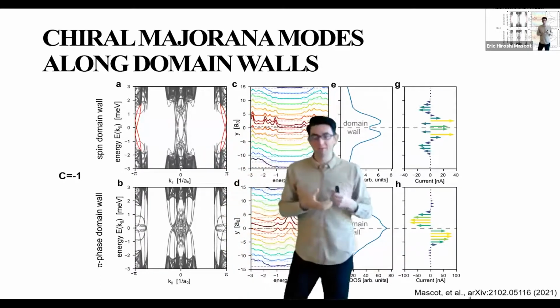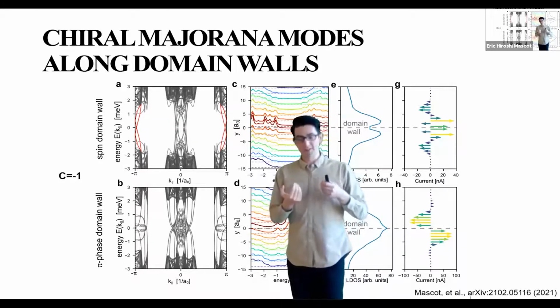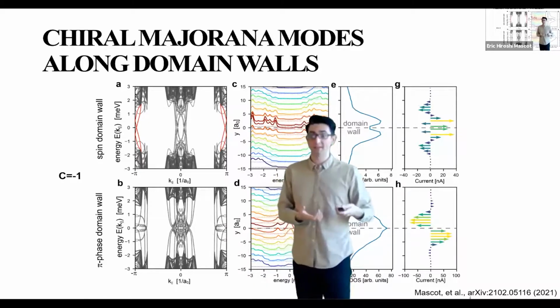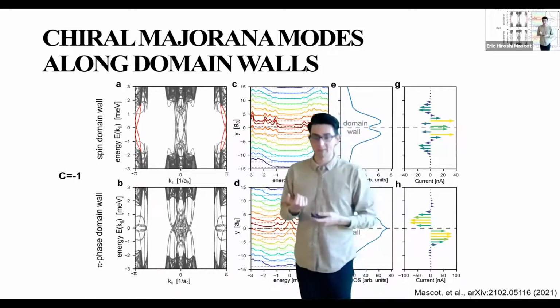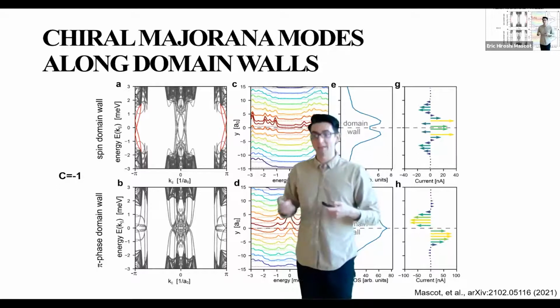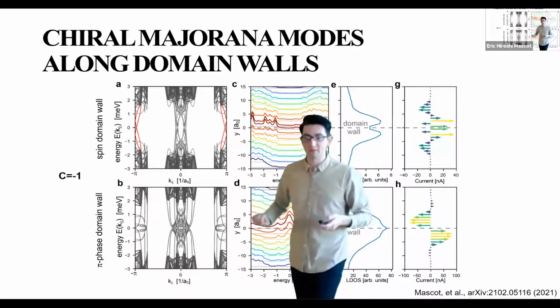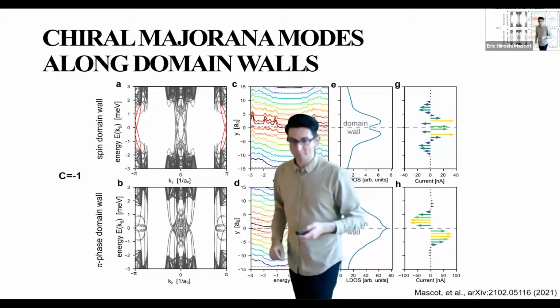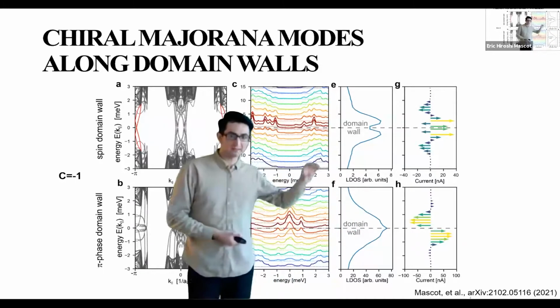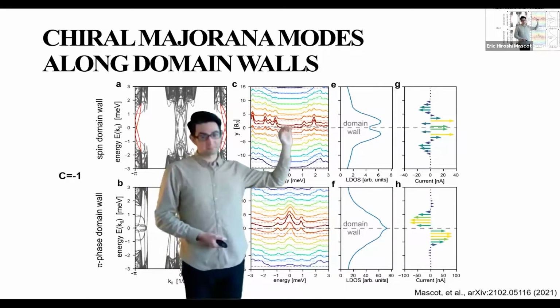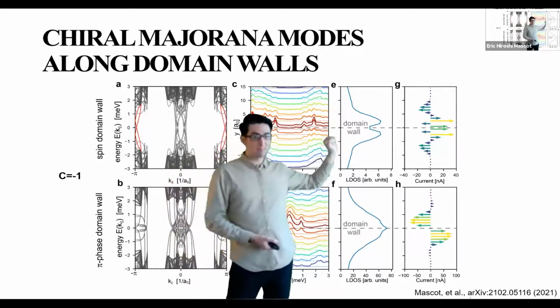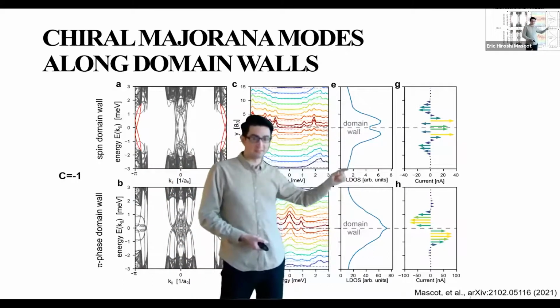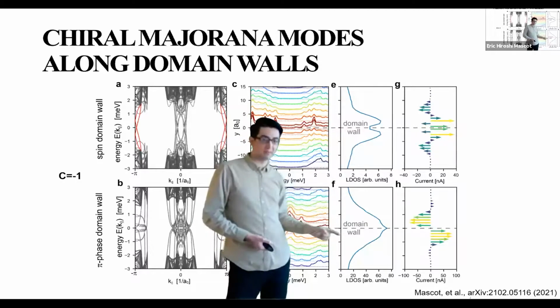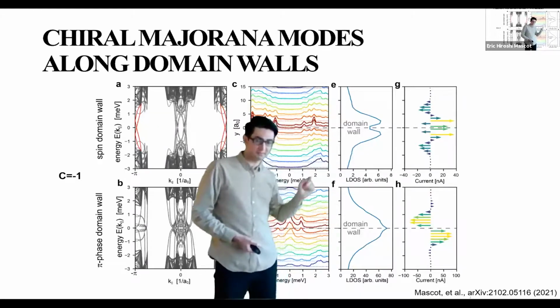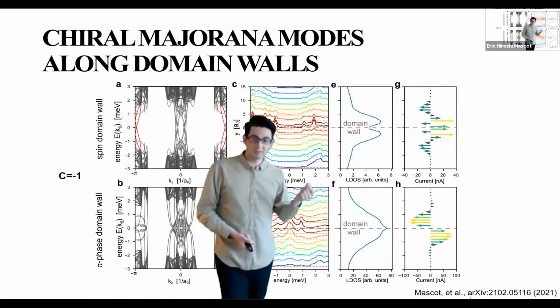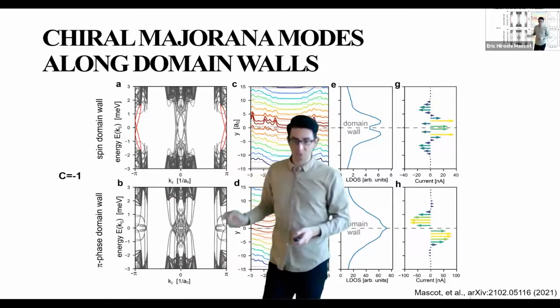And then we also looked at a pi phase domain wall, where the superconducting order parameter changes sign at a domain wall. And in this case, the Chern number doesn't change, and so we don't expect any boundary modes from the bulk-boundary correspondence. And indeed, in the dispersion, it's hard to tell, but these are all not traversing the superconducting gap. And we can look at the density of states of this. And at the domain wall, what we get at zero energy is a state that crosses the gap. And spatially at zero energy, the local density of states looks like this. But if you look between these two different domain walls, they look very similar. So the local density of states is not a marker that we can use to tell the difference between this topological edge state and this trivial edge state.